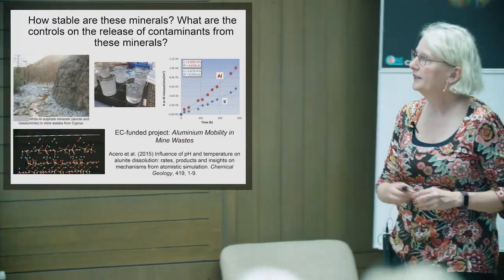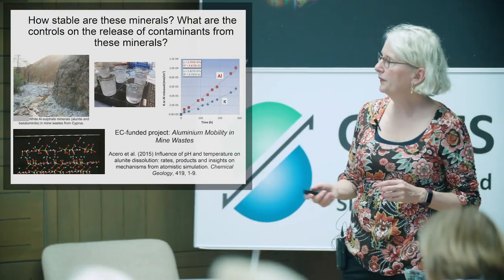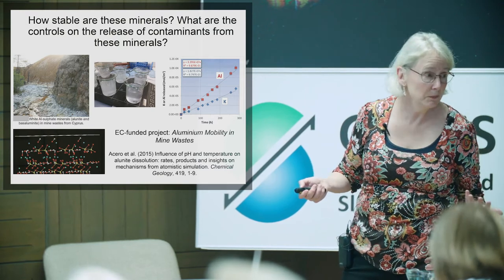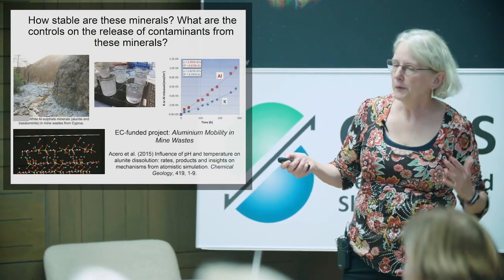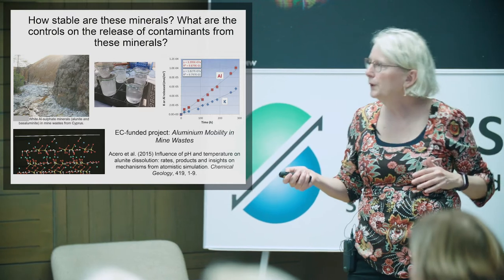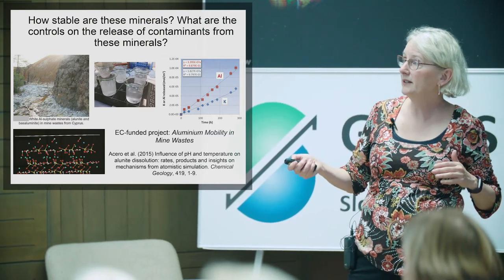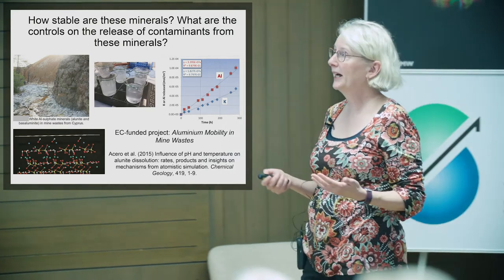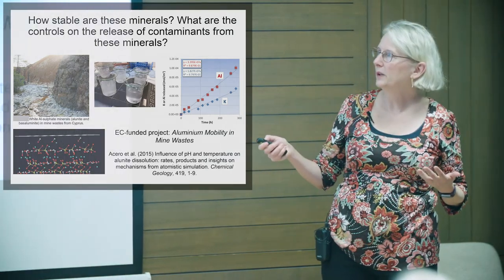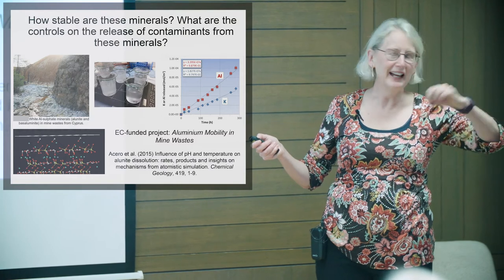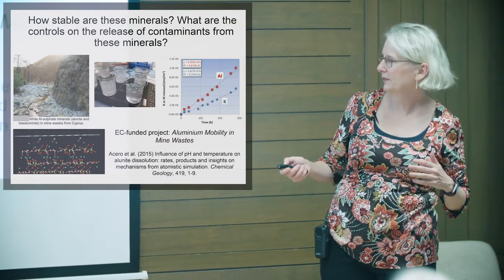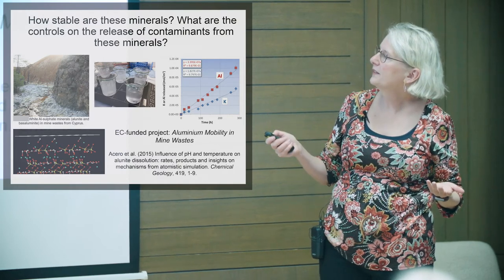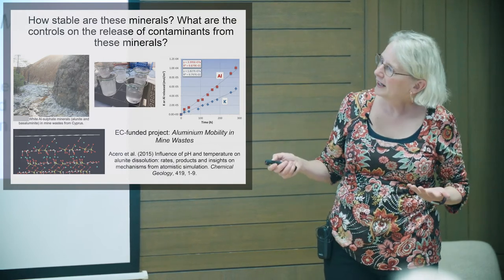Other things that we've done is lab experiments. So this is a postdoc of mine, Patachero, from Spain, who worked on aluminium sulfates in mine waste. So if the pH is a little higher, about pH 4, the aluminium starts to precipitate as this white sort of stuff. And we were interested in how that dissolved. So Pat spent 2 years with lots of beakers dissolving alunite, okay, which is, I haven't got the formula, it's another mineral containing aluminium, and was able to work out dissolution rates of alunite, and then to figure out how